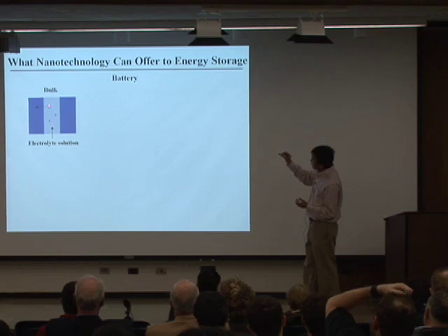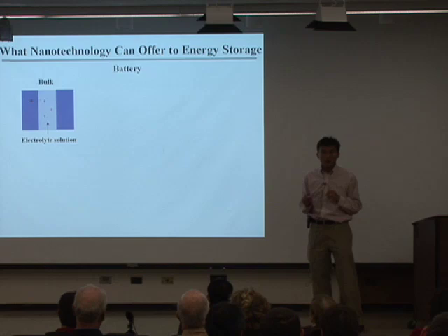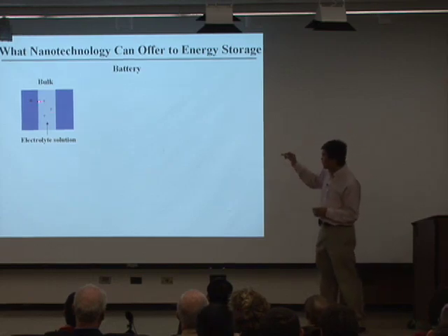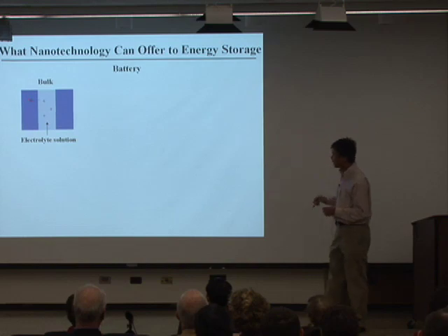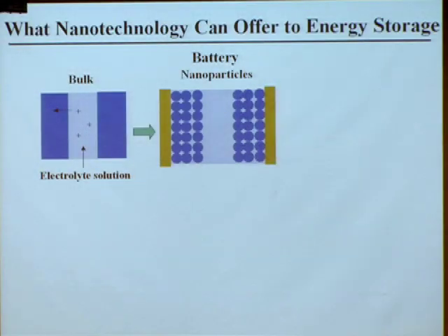To get these metal ions into the bulk of the electrodes, they need to diffuse a long distance, if this is a big piece, to go into the electrode. So you don't like it. It's going to be slow. The way to improve it, if you make this electrode, this big piece, into tiny particles, so each of these particles contacts with the electrolyte. Now the metal ion going in rate can be sped up very fast. The distance required for this ion to go in becomes very small. By doing this, you can improve the speed, the power of your devices. Of course, these particles need to stick onto a metallic collector. So I use this to indicate this is a metal collector.